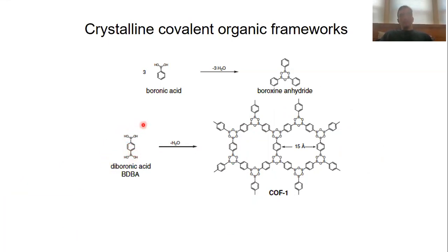As the polycondensation proceeds, water is being eliminated, but by clever choice of the reaction conditions, the water concentration is kept at a level that, on the one hand, still keeps the framework interconnected without depolymerizing it. So you're not going too far in the reverse direction. But on the other hand, we have enough water as a mineralizer available to labilize the boron-oxygen bond.